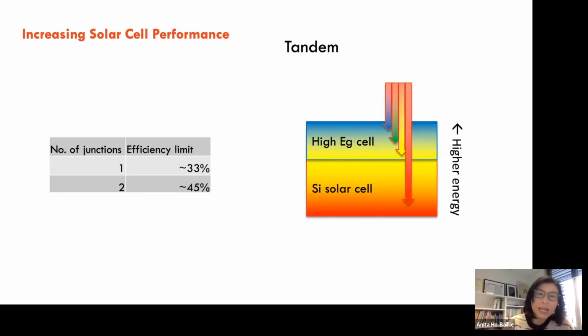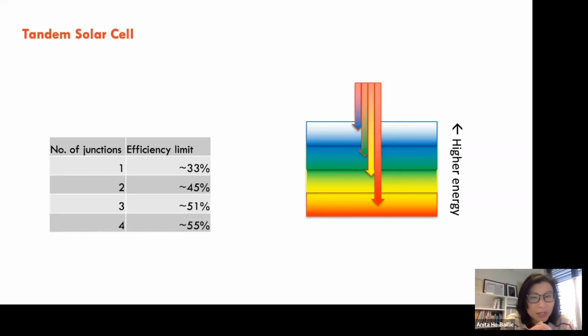So in reality, what we buy from the market, off the shelf, to put on a roof, is at the moment around 20%, and lab-scale cells around 27%. But the efficiency limit is only 33% for one junction, and 45% for 2 junctions. What happens when you increase the number of junctions? The theoretical limit increases to 51 and 55%.